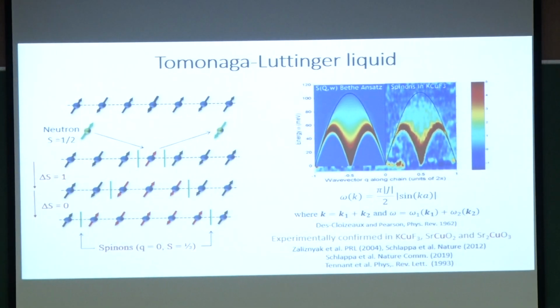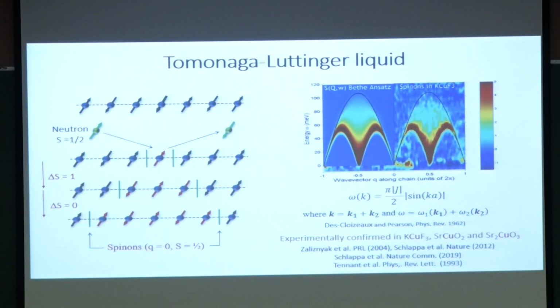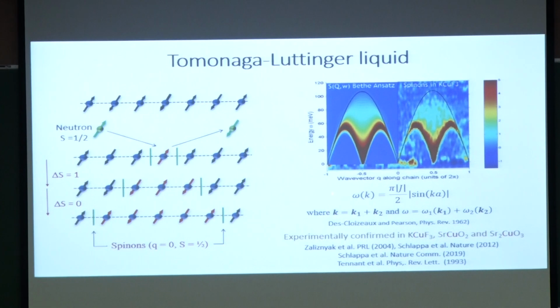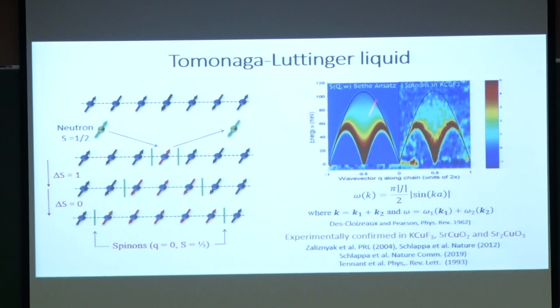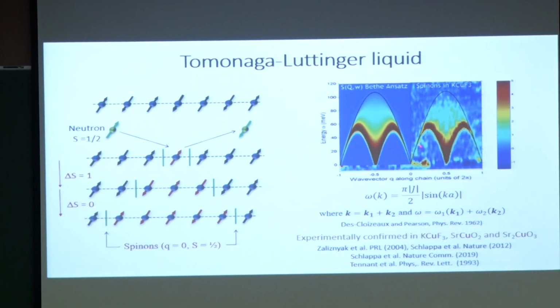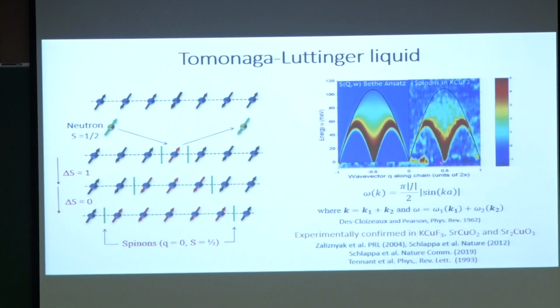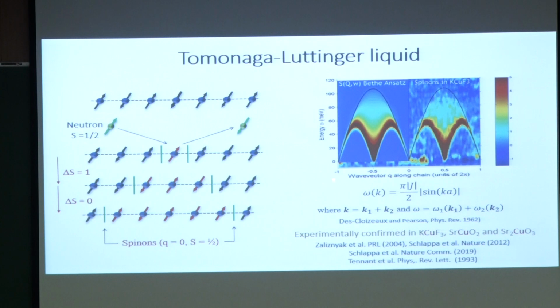So if you have to see whether a material is actually a spin liquid or not, you would do inelastic neutron scattering, and you would see if there is any continuum in the inelastic neutron scattering spectrum that you are measuring. In this case, by default, you see that, and this is known as the two-spinon continuum. This is the experimental data, and this is the theoretical calculation using Bethe ansatz. And this has been shown now on a number of one-dimensional systems.